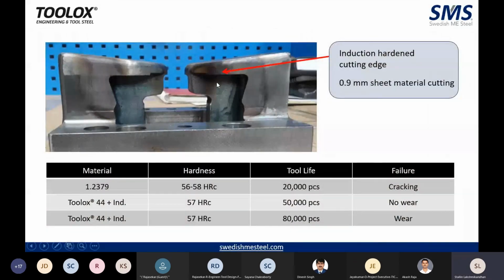So this is a laser hardened, induction hardened edge, 0.9 mm sheet metal cutting. As you can see, the initial material is D2, used at 58 HRC. The total pieces is 20,000. The failure mechanism is cracking. Then we used Toolox 44 plus induction hardening at 57 HRC. It has run for 50,000 pieces. The failure is not cracking, it is no wear. With Toolox 44 plus induction hardening, at 80,000 pieces, the failure is only wear, but not cracking.